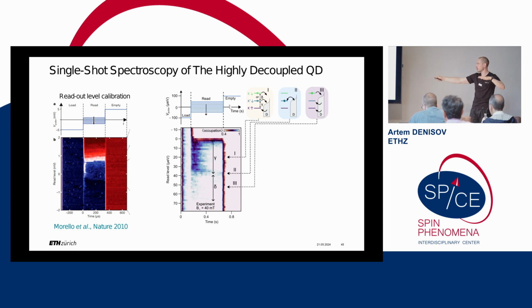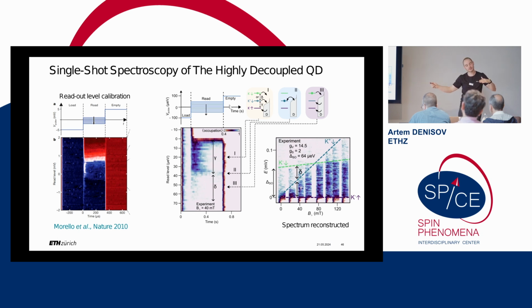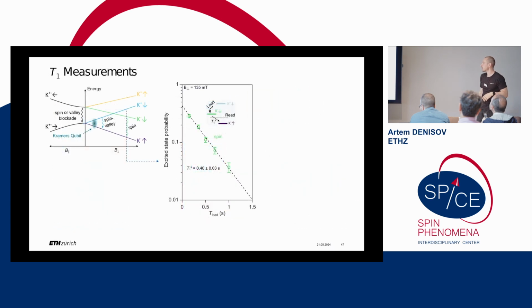is that we can see both excited states, and these excited states, as a function of magnetic field, evolved the same way with a really high G factor and with a crossing point around 80 millitesla. And having this plot in our pocket, we had the freedom to measure the relaxation between the states which we wanted to actually probe and compare spin to spin valley blockade by just moving the readout level from here to here. So this step was quite essential.